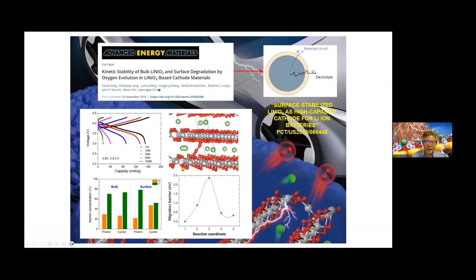So here is the actual experimental data. We did grazing angle X-ray analysis to show the elemental ratio inside the cathode material, initially and after cycling, and at the surface. The bulk inside maintains roughly a 1:2 ratio, but the surface turns from 1:2 ratio to 1:1. So the surface turns into the nickel monoxide rock salt phase, which is not ionically conducting, so the rapid degradation of the material is driven by conversion of the surface layer into the inactive nickel monoxide layer.